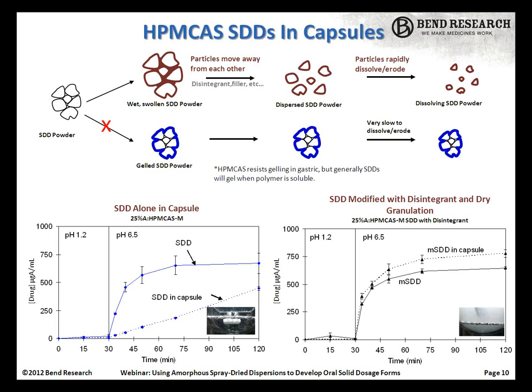We have here on the next slide an example of taking an HPMCAS SDD and just placing it into a capsule. What can happen is, as the water dissolves the capsule, it can cause the polymer to stay closely associated with itself, and as the water comes in, it can potentially gel the material. So what you end up with is a large mass that has a low surface area, and it becomes difficult to get rapid dissolution.